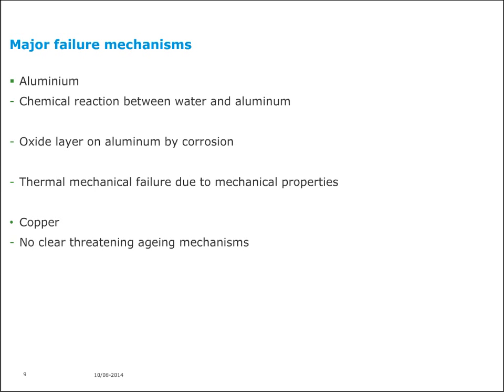We start with aluminum. There is in the literature information given about the chemical reaction between water and aluminum. When water enters the conductor, then you get aluminum oxide and hydrogen. Hydrogen is developed in that process, and that can be at relatively high pressures, damaging joint structures and resulting finally into failure. This mechanism is not generally recognized, and we will discuss that later, as not all utilities have in their statistics the link with the conductor material. So when there is a failure, it is not always recognized whether it is in a copper or in an aluminum conductor. But in the literature, some laboratory experiments are described that indicate clearly that this is a threatening failure mechanism.